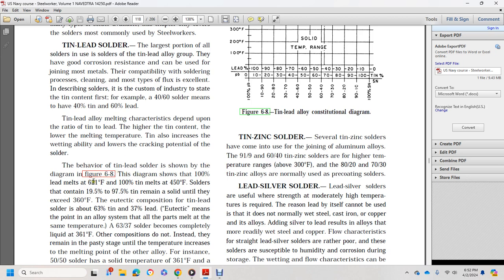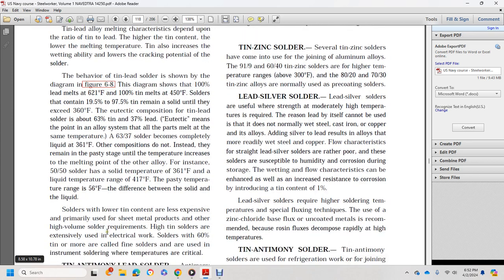The diagram shows 100% lead melts at 621 degrees Fahrenheit and 100% tin melts at 450 degrees Fahrenheit. Solders that contain 19.5 to 97.5% tin remain solid until they exceed 360 degrees Fahrenheit. Eutectic composition tin-lead solder is about 63% tin, 37% lead. Eutectic means the point in an alloy where all the parts melt at the same temperature. 63-37 becomes completely liquid at 361 degrees Fahrenheit. Other compositions do not. Instead, they remain in a pasty stage until the temperature increases to the melting point.